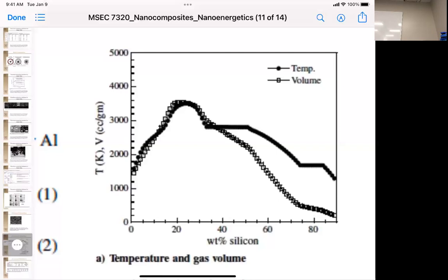And then our gas volume changes as you go down to 100% silicon, because now you have less of the Teflon and you're burning it as silicon dioxide. So of course your temperature goes down and your volume goes down. Okay, so that means that we have a problem if you're burning your silicon in air, you're going to have that formation of silicon dioxide, which changes the mechanism. When it was generating the silicon tetrafluoride, you're in that vapor phase reaction. And when it's in the silicon oxide, you're in that crust phase reaction.